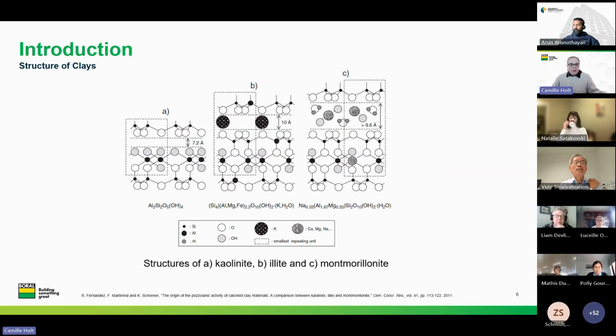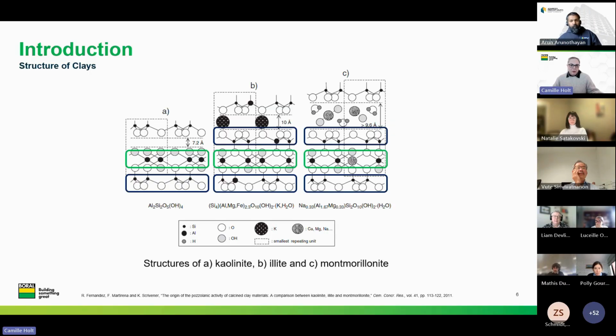If we compare the structure of kaolinite with illite and montmorillonite, we start to get a feeling why kaolinite is the preferred clay. Each is made up of sheets of alumina and silica, but kaolinite is comprised of one silica sheet for every alumina sheet, whereas illite and montmorillonite have two silica sheets for every alumina sheet. The alumina is sandwiched between the silica sheets, making the aluminium atoms harder to get to, and this makes the clay less reactive.